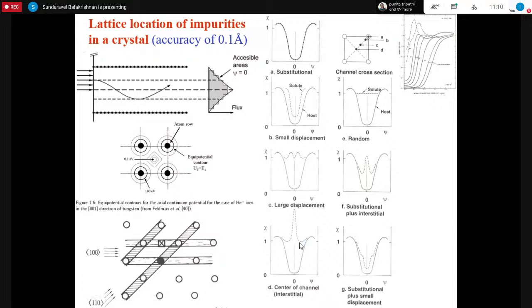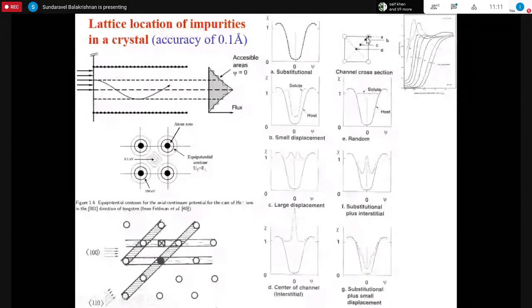Suppose the crystal has some other defects, then the impurity atom, say this is the host lattice position, and this dark spot is the impurity. If it is moving towards the center of this channel, from that one we can find what is the lattice position. Even for a small shift of 0.1 angstroms, we can see much change in shift positions.